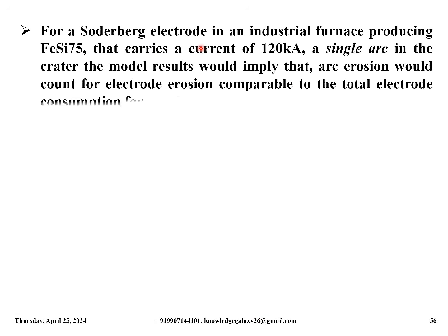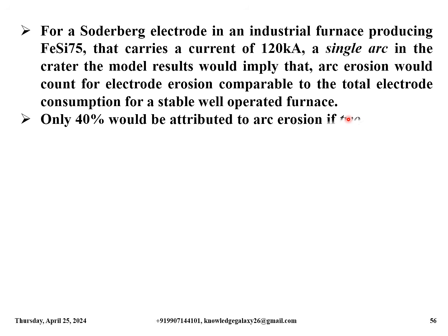For a Soderberg electrode in an industrial furnace producing ferrosilicon 75% grade that carries a current of 120 kA, with a single arc in the crater, the model results would imply that the erosion would account for electrode erosion comparable to the total electrode consumption for a stable, well-operated furnace. Only 40% would be attributed to arc erosion if two arcs do the job.